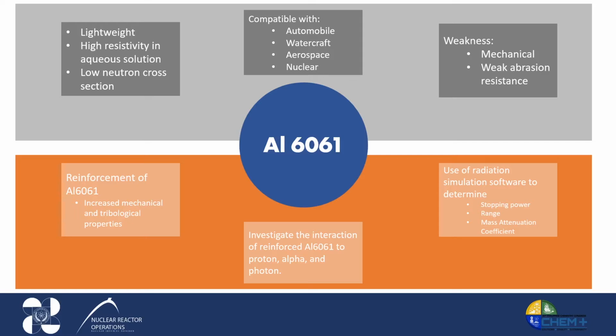One study concluded that hybrid aluminum 6061 matrix composites with boron carbide, zirconium oxide, and silicon carbide of varying compositions have better wear resistance due to the mechanical properties of zirconium oxide and silicon carbide. Furthermore, several studies have reported that the addition of metal reinforcements to aluminum 6061 improves its mechanical properties. As mentioned earlier, one application of aluminum 6061 is for nuclear reactors, as a material for nuclear support structures.